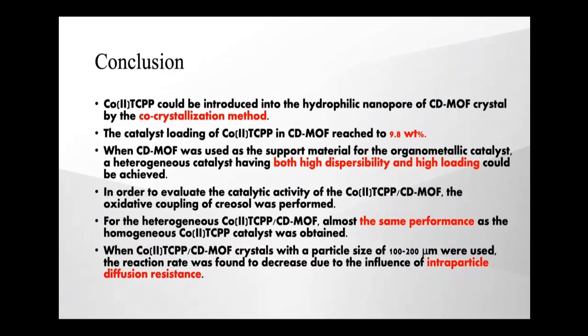We summarized our conclusion as follows. Cobalt TCPP could be introduced into the hydrophilic nanopore of CDMOF crystal by the co-crystallization method. The catalyst loading of cobalt TCPP in CDMOF reached 9.8 wt%. When CDMOF was used as the support material for the organometallic catalyst, a heterogeneous catalyst having both high dispersibility and high loading could be achieved.